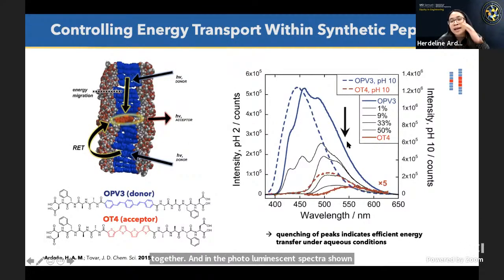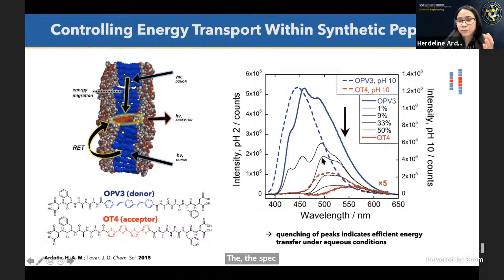And this is, in fact, what we saw when we merged them together, in the photoluminescence spectra shown on the right. Even with just 1% of the acceptor, we can see a decrease in the intensity of the photoluminescence that we see in the donor. And as we increase the percentage of the acceptor unit, the spectral profile quenches more and more and mimics the profile of the acceptor.